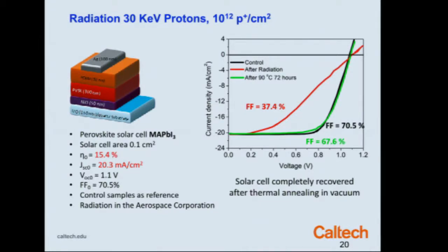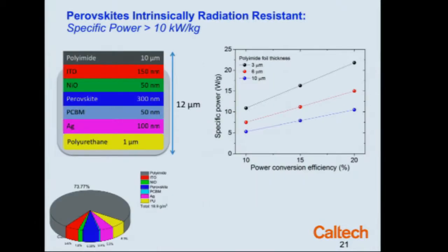This is a remarkable statement. It says that this is a potentially radiation-hard, ultralight photovoltaic material. And so if we can simply encapsulate this in lightweight polymer materials, I think it's easily achievable that we can get into the maybe 20 to 25 kilowatts per kilogram specific power density. For reference, today's spacecraft are typically in the few hundred watts per kilogram range.